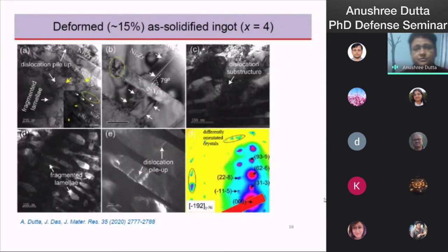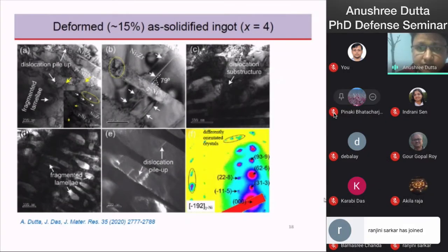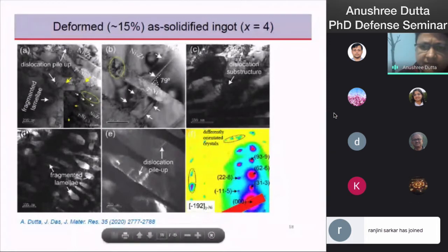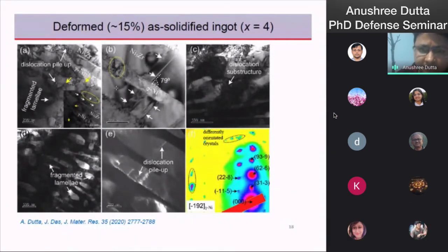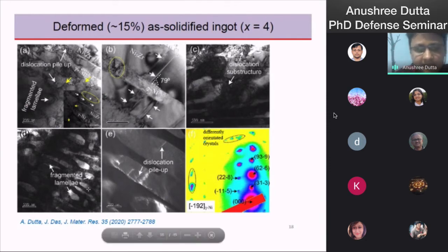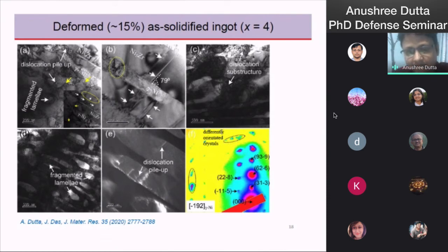Now, the transmission electron microscopic structure of the as-solidified ingots deformed up to 15% shows that several dislocations are introduced in the microstructure after deformation. We can find the dislocation substructure, dislocation pile-ups and several fragmented lamellae after heavy straining. Some of the lamellae overlap with each other, and we can find several faults and band structures. The lamellae become fragmented, and in the SAD pattern differently oriented crystals have been observed, which indicates the introduction of dislocations and lamellar bending due to the heavy straining of the composites.